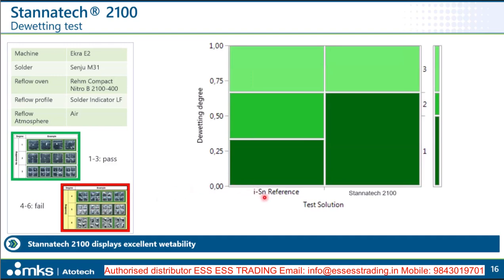And we compare again the reference versus the Stannatech 2100, and we see that for most cases we have a solder grade of 1, 2, and 3, but no failed conditions, so no 4, 5, or 6 is observed, neither for the reference process nor for the Stannatech 2100. Also here, we see a bit more of the grade 1, so again slightly better than the reference process.